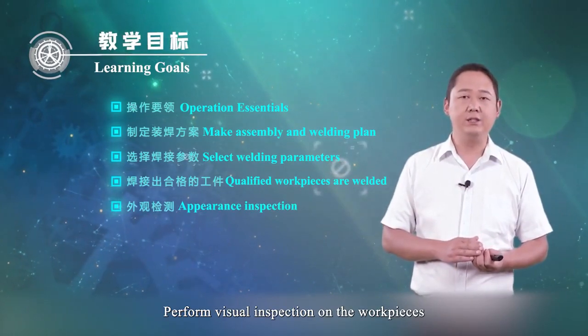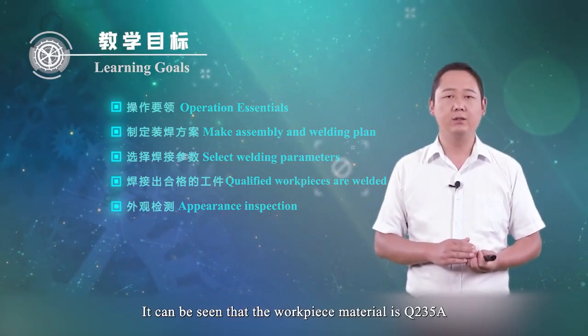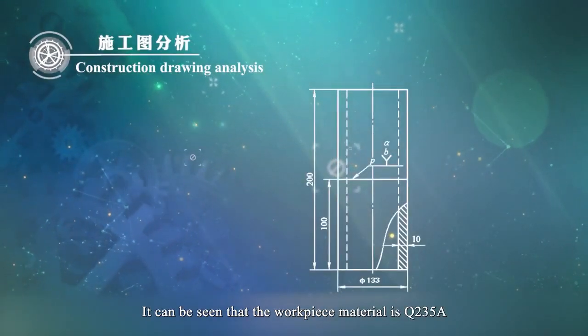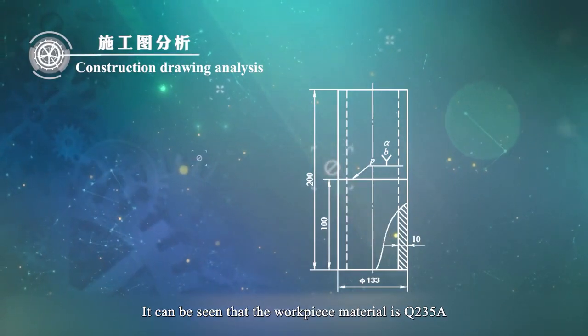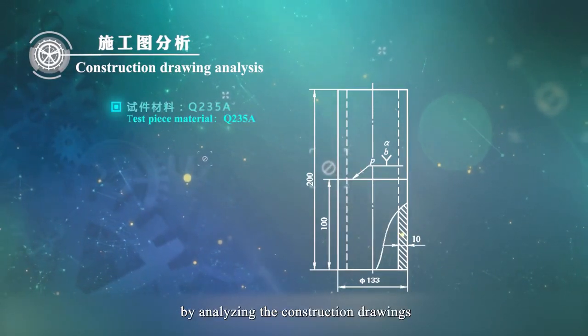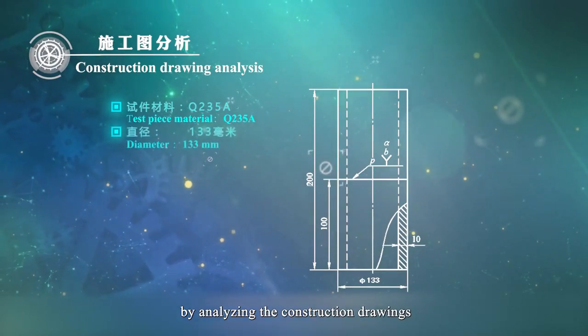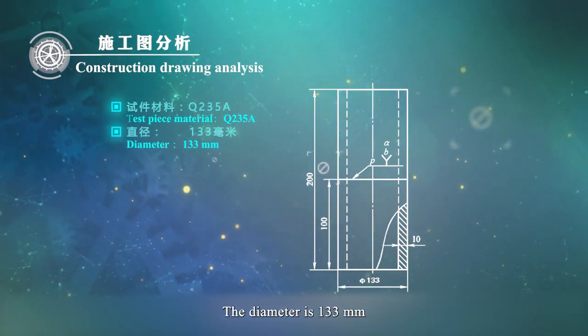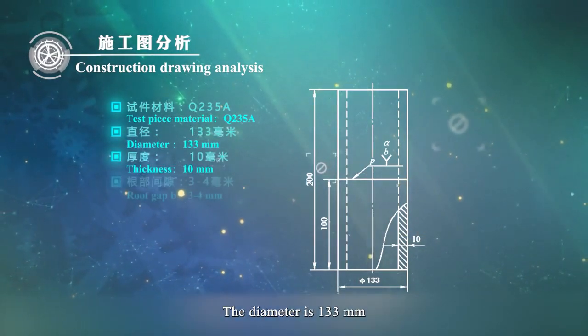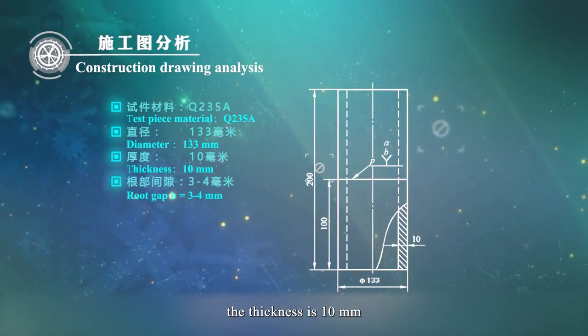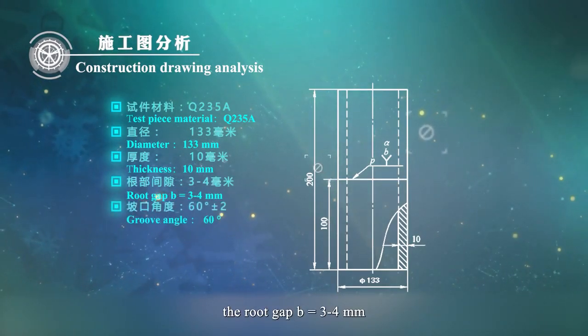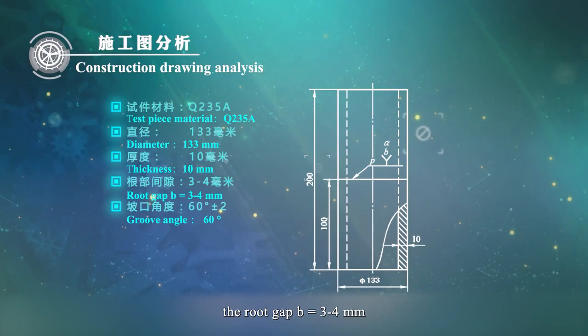Perform visual inspections on the workpiece. It can be seen that the workpiece material is Q235A by analyzing the construction drawings. The diameter is 133 mm. The thickness is 10 mm. The root gap B is 3 to 4 mm. The groove angle is 60 degrees.